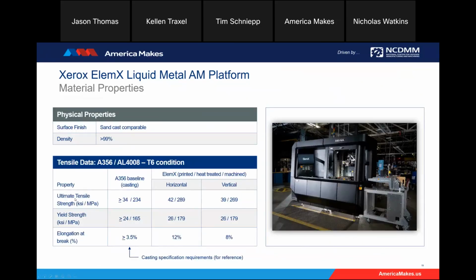Shown here is a summary of the basic physical and mechanical properties, as I mentioned. I talked a little bit about it already, but the surface finish is equivalent to a sand casting. It tends to be right around 28 to 30 micrometers Ra, which is the average surface roughness. It does vary a little bit relative to the build orientation, the surface relative to the build orientation. So downward facing surfaces, for instance, tend to be a little bit rougher than a top flat surface. We do have quite a bit of characterization data on surface finish that we can provide upon request as well. That's no problem. And then we routinely get densities greater than 99%, even 99.5% on the printed parts.